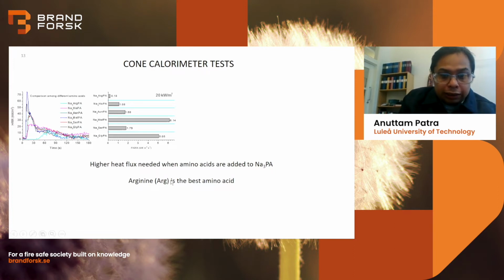So arginine is the best amino acid among the things we have chosen. We have tested a lot of amino acids and even their mixtures, but arginine is definitely the best. The samples we made with arginine always self-extinguish if they catch fire, but in most cases, they don't even catch fire. So now we wanted to check how much arginine is best.